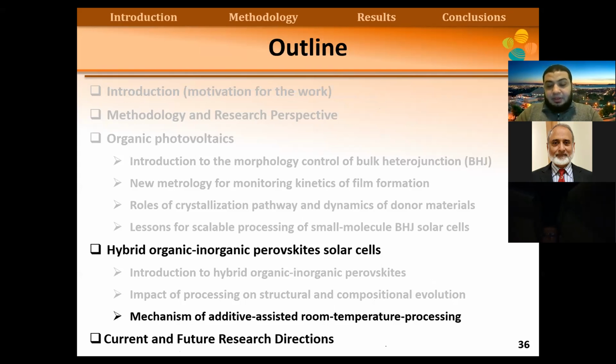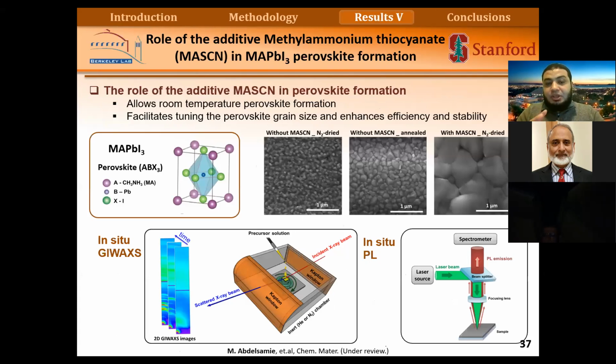So we move now to the final topic, in which we apply room temperature processing. And the main benefit of room temperature processing is also related to scalability. If we use room temperature processing, it can help us to scale up the process much more easily than if we use annealing. And with this, we use some additives in order to tune the microstructure and also to help this process happen at room temperature without the need for thermal annealing at all. And as we can see here, we have methyl ammonium thiocyanate.